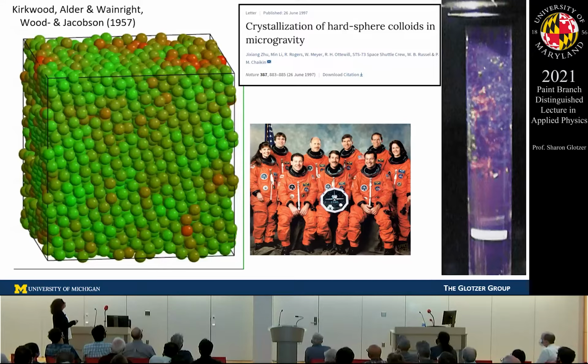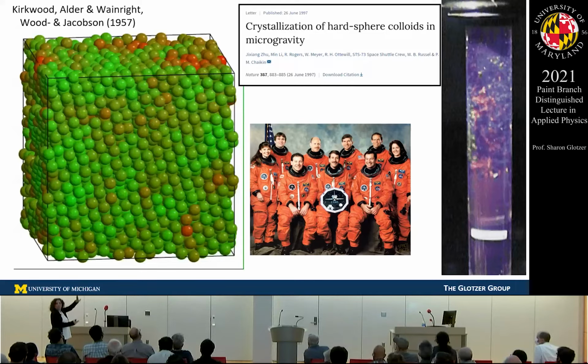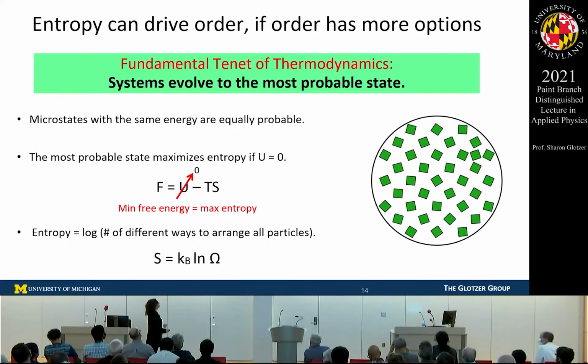And this is a picture of this tube of toluene with polymethyl methacrylate particles inside that are density matched so that they float, and the index of refraction of the particles and the solvent are also matched so that it screens out all the van der Waals interactions. They wanted to get to microgravity, so this was the best you could do, to put it on the space shuttle to show there are no gravitational effects, and it really does form a crystal, which you can see from all these beautiful colors. So that was the definitive experiment that said without any explicit attraction, you can get ordering to occur.